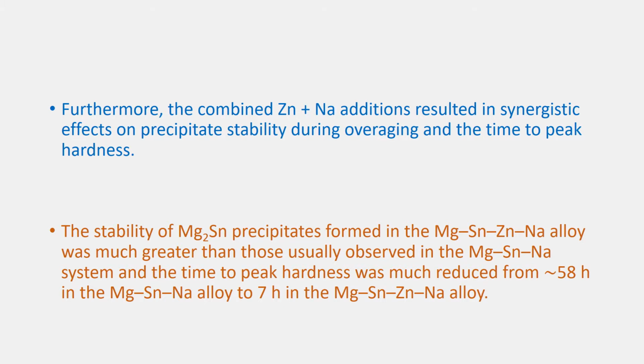Furthermore, the combined zinc plus sodium additions resulted in a synergistic effect on precipitate stability during overaging and the time to peak hardness. The stability of the Mg2Sn precipitate formed in the magnesium, tin, zinc, sodium alloy was much greater than those usually observed in the magnesium, tin, sodium system, and the time to peak hardness was much reduced from 58 hours in the magnesium, tin, sodium alloy to 7 hours in the magnesium, tin, zinc, sodium alloy.